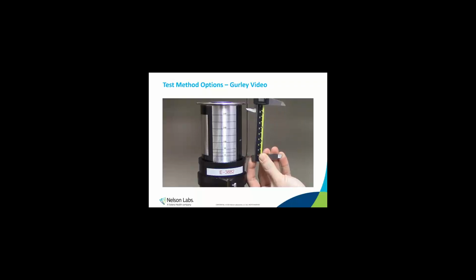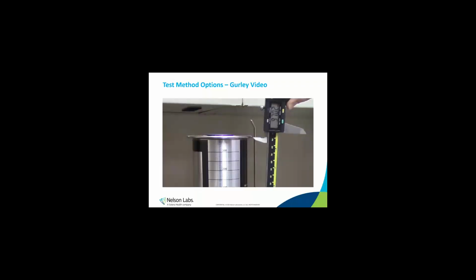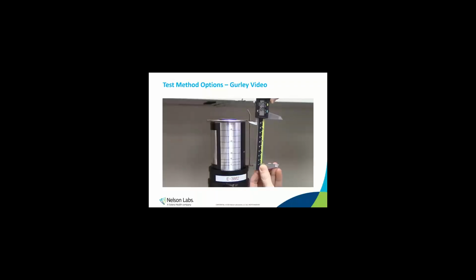We're going to measure this distance again after an hour. And if the difference between the 2 measurements is less than 1 millimeter, then the sample passes. If it's greater than that, then that probably means that either we didn't do a good job measuring, or the sample had a slight porosity to it and the cylinder dropped a little bit. Well, let's look now at this aerosol challenge test.